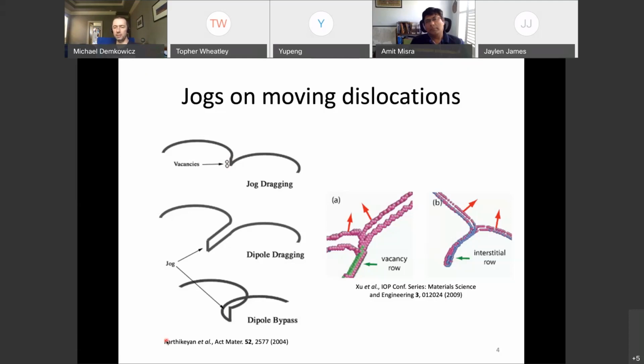I have two questions. Yep. First is that I remember you mentioned the free energy for the double kink nucleation given by Argon is delta G equal to, there is a power term that is 1 minus tau over tau max. Yeah. So that means basically we have a criterion that tau max is required to nucleate kinks. Right. So I'm just mechanically using mechanical loading alone, because of course, the idea there is that by the time you reach tau max, there is no more activation energy to nucleate a double kink. Right. But you can still nucleate it at a lower stress. It just requires some thermal activation.